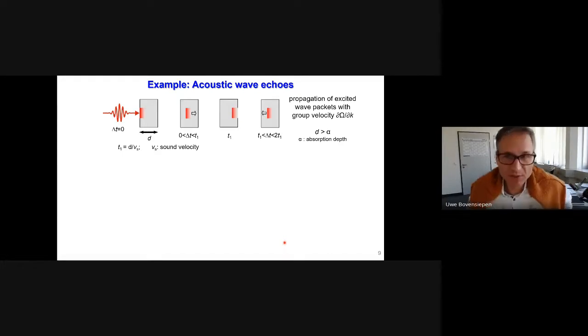So let's start with a simple example, acoustic wave echoes. We take a thin film of thickness d, which is larger than the optical absorption depth of a pump laser pulse. So we only excite here, within the optical penetration depth, some region of the sample. Then there's a gradient in excitation, and after some time, this excited region has started to propagate into the material according to the group velocity of the formed wave packet. When it reaches the backside, it cannot propagate further, and it will be reflected. So we have some echoes.